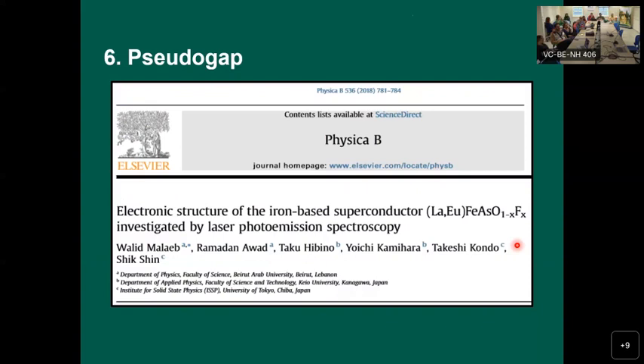So we have electron pairing, but this occurs only in the superconducting state, and it is responsible for the phenomenon of superconductivity. Great. But we noticed also that above the Tc, in the normal state, we also have pairing, but it doesn't lead to superconductivity. So that was strange. We call it the pseudo gap. And there are two schools here. Some people believe that it is directly related to superconductivity, but there is no coherence. That's why the word coherence is very important for us. Some other people believe that it's against superconductivity.